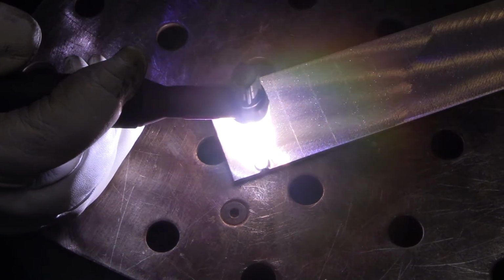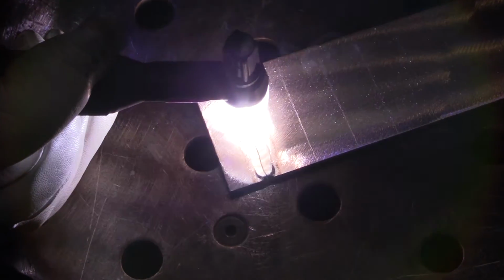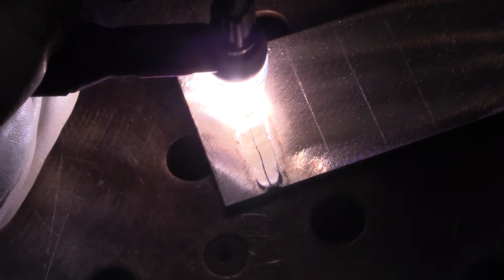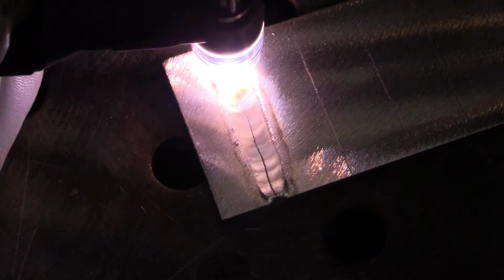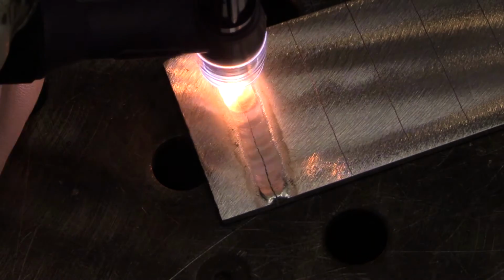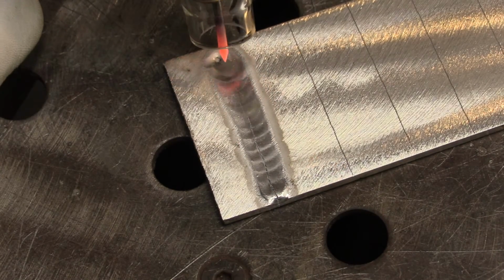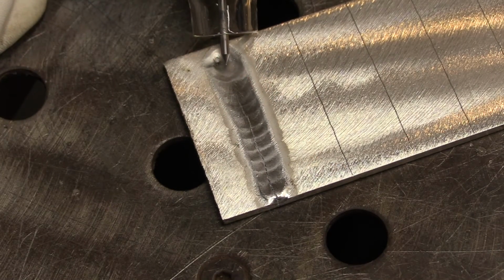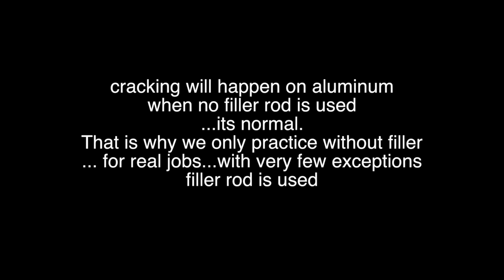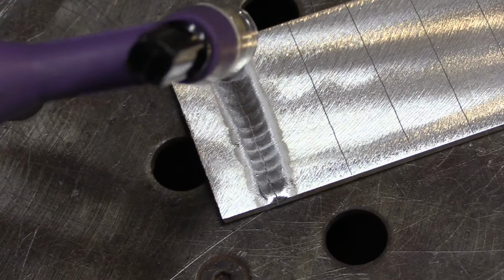I want to just show this in its entirety, this one bead, because there's something you'll see right now, and it's a crack right down the middle of the weld, and that is typical of aluminum. Aluminum has a characteristic called hot shortness. It's going to crack without filler metal almost every time. Not a problem for practice. We need to practice and build these motor skills. Just know that's why we use filler rod.